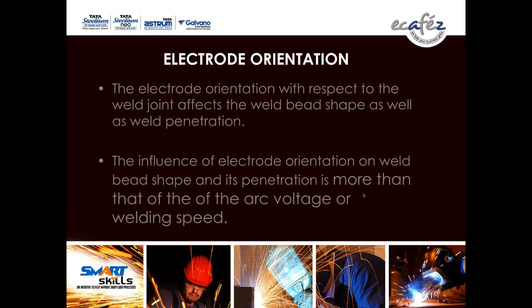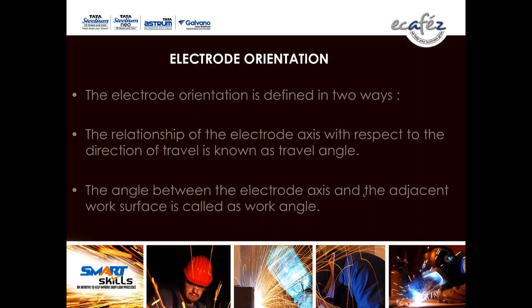So, electrode orientation. The angle of the torch is called electrode orientation. The electrode orientation with respect to the weld joint affects the weld bead shape as well as weld penetration. Very important. For good quality welding, the main point is good penetration. The influence of the electrode orientation on weld bead shape and its penetration is more than that of the arc voltage or welding speed. The electrode orientation is defined in two ways.